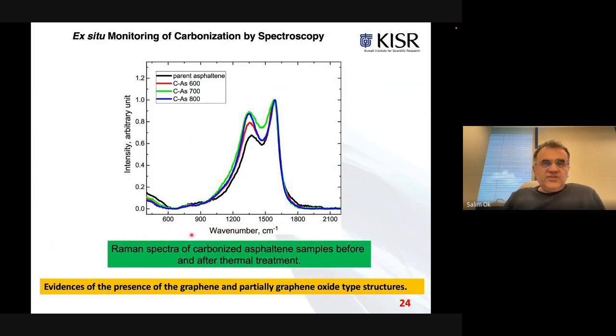In addition to such characterizations, we also focused on characterizing the carbonized asphaltenes by spectroscopy, especially Raman spectroscopy. We recognized that asphaltenes are derivatives to graphene. So when we do the thermal treatment, as you can see, from raw parent asphaltene to the thermally treated ones, there is a shift in different bands of the Raman spectra. At the same time, we recognized that carbonization of the asphaltenes resulted in graphene type structures, and even partially graphene oxide type structures.